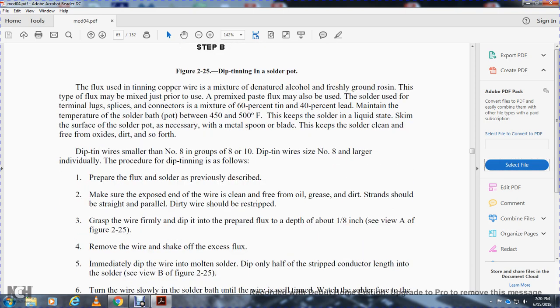Dip wires smaller than number 8 in groups. Dip wires number 8 or larger individually. The same procedure for dipping wires is followed. Prepare the flux and solder as previously described. Make sure the exposed end of the wire is clean and free of oil, grease, and dirt. Strands should be straight and parallel. Dirty wires should be restripped.